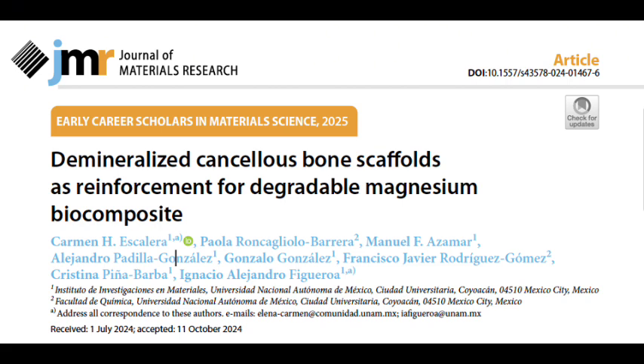Yeah. It led to another interesting discovery. Oh. They found a new phase forming. A new phase? Yeah, an intermetallic compound called Mg2Ca. What is that? It's an alloy of magnesium and calcium. Oh, okay. And they didn't see it in the composite with the carbon coating. So it only formed in the one without the coating.